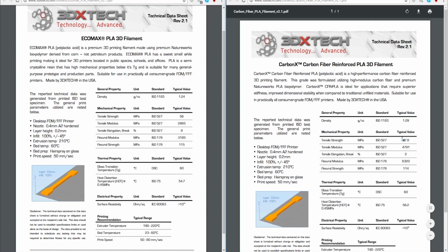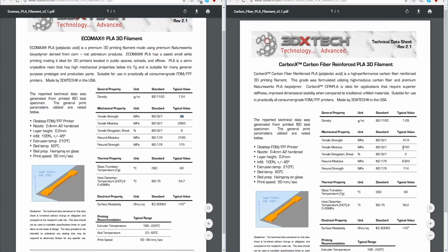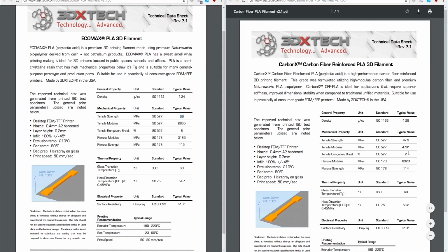Because most of the time, in most parts, you're going to be below this and below this, but even if you're below this by like 30, you're at like 30 megapascals load, you're gonna make way better, stiffer components out of 4791 than 2865. So any sort of application where you want the part to be stiffer, so not deform as much, you're gonna want the carbon fiber to be inlaid inside. But we have a downfall there. Because of the stiffness, we have a drastic loss. Generally, a material that has more stiffness is not as ductile, is more brittle, so that means that it tends to snap without bending too much.